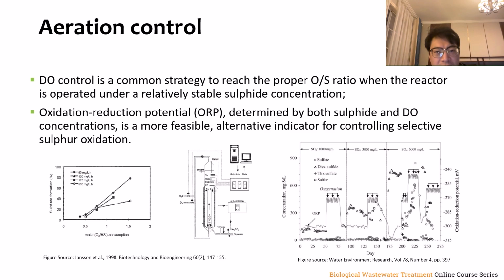However, controlling dissolved oxygen presents its own set of challenges. According to literature research, one of the main difficulties is the dynamic nature of DO concentrations. As oxygen is continuously consumed during the bioreaction, its concentration in the reactor fluctuates, which can make it challenging to maintain the desired O/S ratio consistently. This fluctuation can affect the efficiency of the sulfur oxidation process, potentially leading to less than optimal system performance.